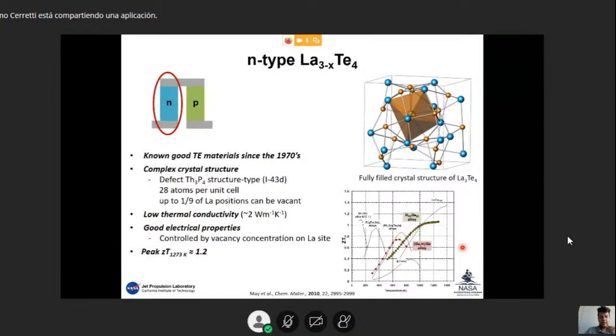The materials that we're currently studying for future generations of RTGs are, on the N side, lanthanum telluride. It's a thermoelectric material already known since the 70s, characterized by a complex crystal structure, therefore low thermal conductivity, and it has good electrical properties that can be manipulated by playing with this X, pulling out some of the lanthanum atoms from the structure. It has a peak ZT at 1273 K of about 1.2.